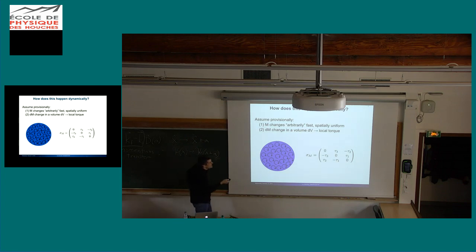Then we can sort of represent the stress inside the crystal in a continuum model as this kind of off-diagonal stress tensor. So those of you versed in continuum mechanics may start to dig out a crucifix or something against this off-diagonal stress tensor, because this is typically not allowed because it doesn't conserve angular momentum. But that's what we're trying to do, right? We're trying to model a transfer of angular momentum from the spin system into the lattice. And so as long as this doesn't exist for a long time, we're actually good. This is representing the transfer of angular momentum.